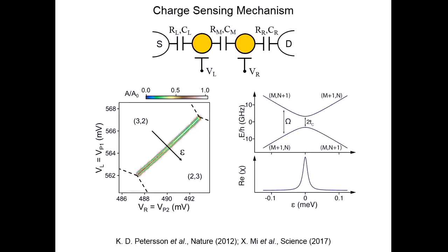Here's an example zooming in on the 3-2, 2-3 electron transition. The total number of electrons in the device is 3 plus 2, 5. Here we have 3 in the left dot and 2 in the right dot. Here we've just tilted that double well potential and moved one of these electrons over to the other side. Okay. What's plotted here is the transmission through the cavity as a function of these voltages. And you can see that there's a big cavity response here. The transmission through the cavity almost goes to 0 as we move that electron from left to right across the double well potential. And why is that?